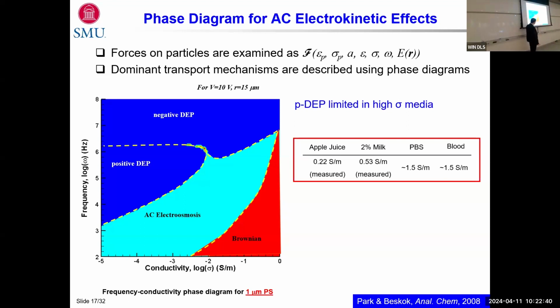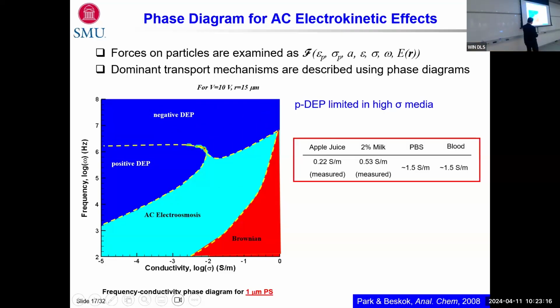And we have done systematic studies for 1 micron polystyrene particles to show that at different frequencies you'll see different things. Well, this picture tells me that at high frequencies, mostly we expect negative dielectrophoresis theoretically. And there's a zone of positive dielectrophoresis in a certain frequency range. And that's very much a function of the conductivity. So at high conductivities we have no chance of positive DEP. And also there are other effects like Brownian motion of particles always there, but then AC electroosmosis may be dominant. And at one point, as the double layer thickness gets smaller and smaller, that's not important altogether.